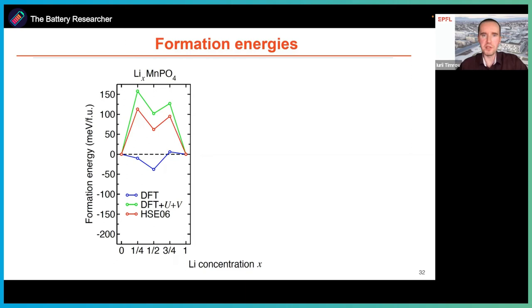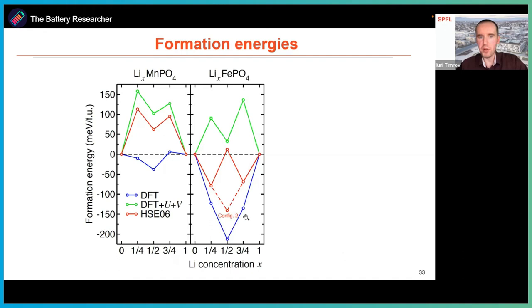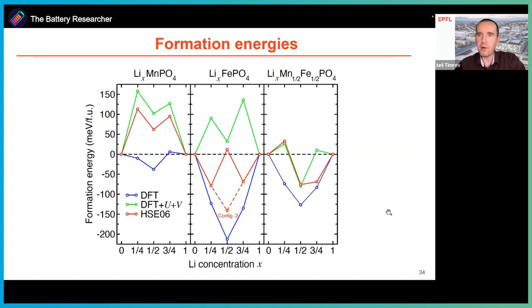In the case of iron, DFT fails because formation energies are negative, and also the hybrid functional fails, which is quite surprising. And only one method, DFT plus U plus V, gives the correct result because the formation energies are positive, because in experiments, again, there is a two-phase process. And the most challenging case is this mixed manganese iron olivine. We need to consider each concentration with more care. So when x equals 1/4, we obtain that the hybrid functional and DFT plus U plus V give positive formation energy.